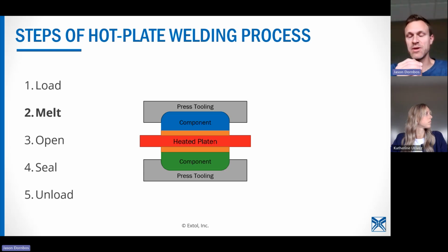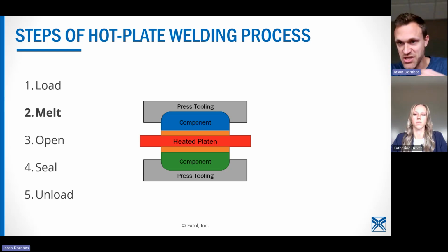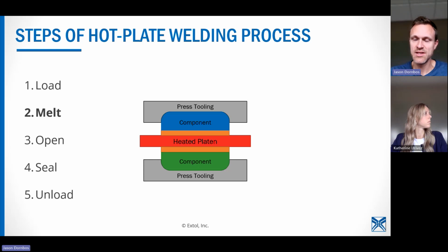But the other thing that's really a benefit of the hot plate process is that we're melting the plastic surfaces on a machined heated tool. That heated tool is very precisely machined so that we're going to melt away any of the molding irregularities that might be on your weld surface. So if you have high and low spots, areas where there's material sink, we're melting the plastic onto the heated tool and we're eliminating all of those inconsistencies on the top of your part.